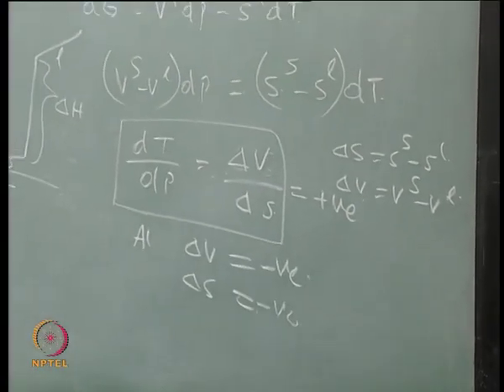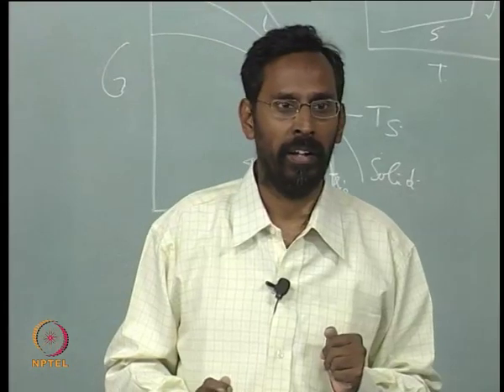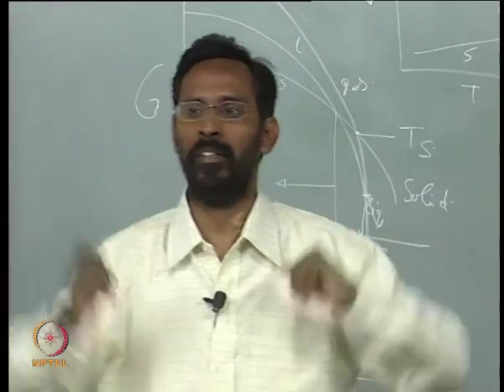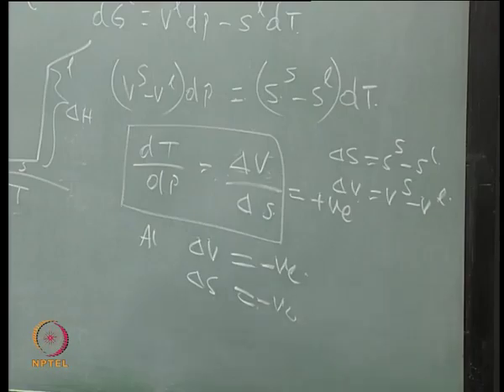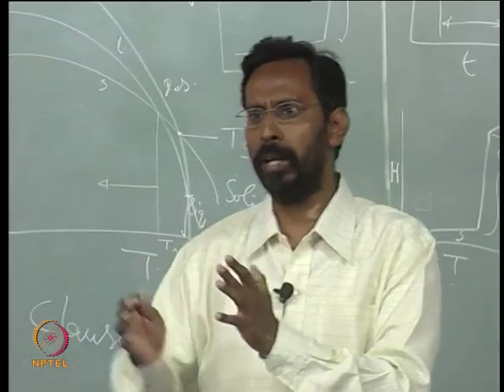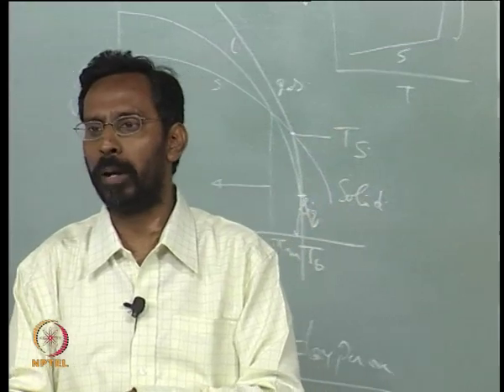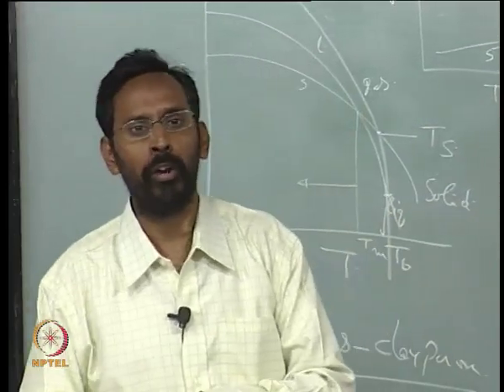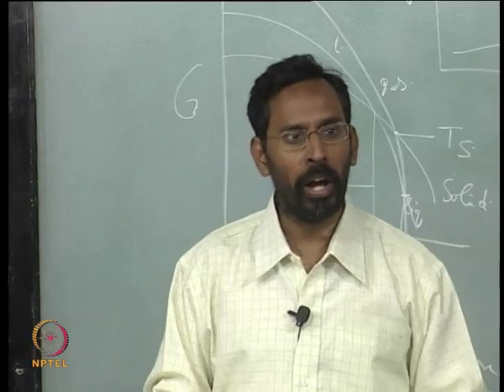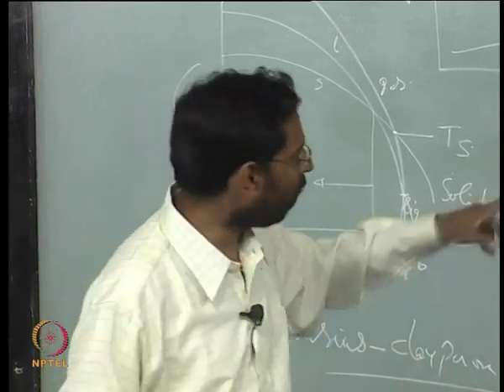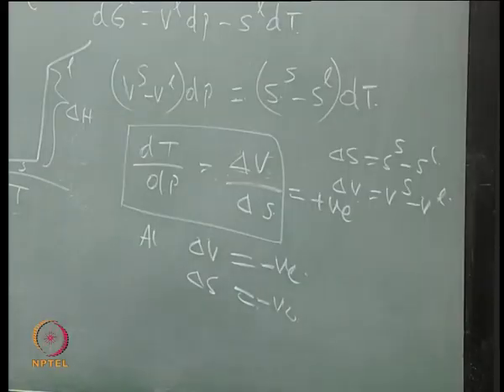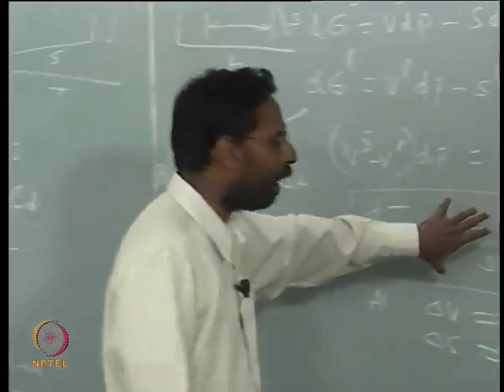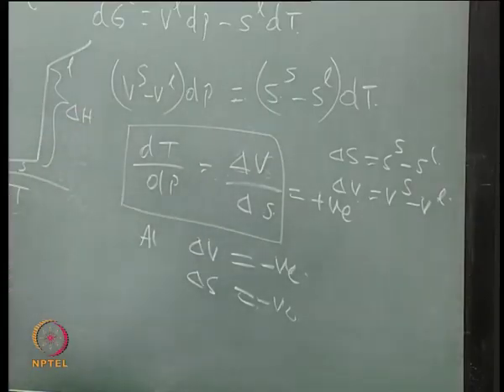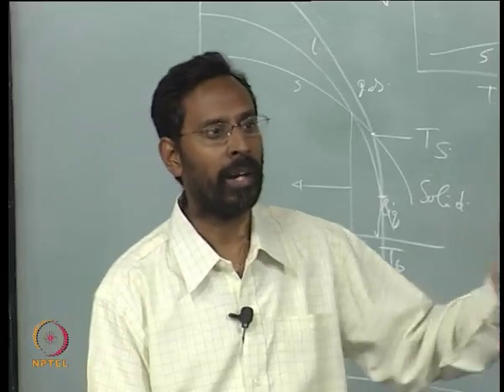What does that tell you? It tells you that if I increase the pressure, the melting point of aluminum will increase. If I decrease the pressure, the melting point of aluminum will decrease. That means the same aluminum, instead of melting it at atmospheric pressure, if I melt it at 10 to the power minus 6 torr vacuum, it should melt at a lower temperature than 660. Unless I know this Clausius-Clapeyron equation, I would not be able to know that. This is a very crucial thing, and all those people who do secondary steel making should know this, otherwise they will not know to what temperature they should heat the steel to melt. All the secondary steel making is vacuum refinement.